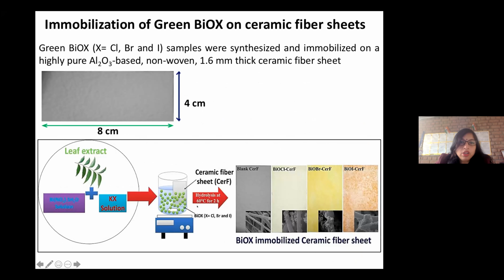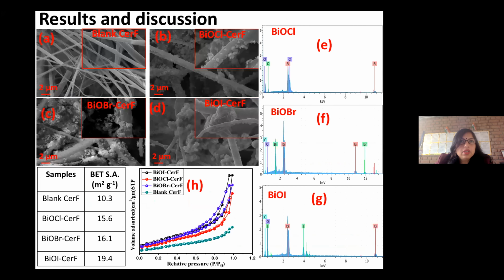Then the material was immobilized on the ceramic fiber. The different bismuth oxyhalides were immobilized on the ceramic fiber sheet. These are the images. You can see this is the SEM image of blank ceramic fiber, this is chloride ceramic fiber, and iodide, bromide. In all, the SEM images showed that the material has been immobilized properly. When you see the BET surface area, in the case of BiOI, it was more, 19.4. By BET it was proven, and the EDX studies showed that all the elements were present in the material.